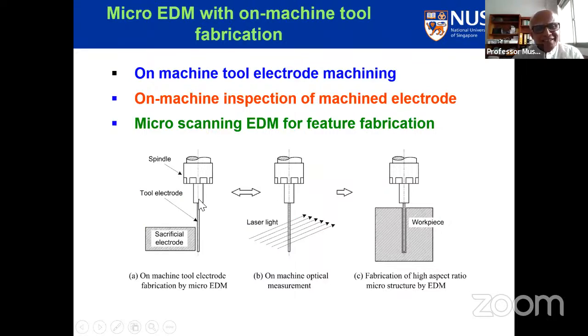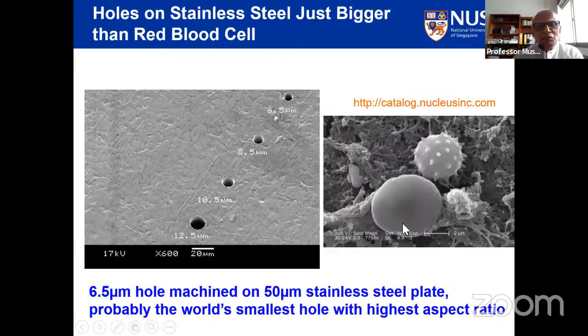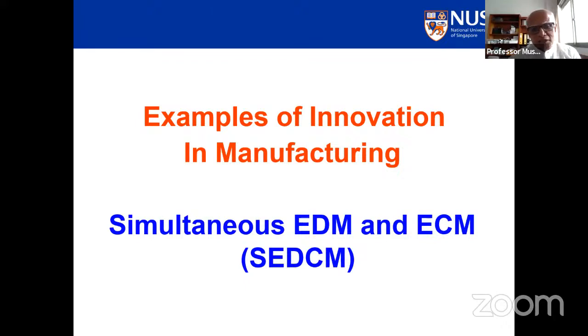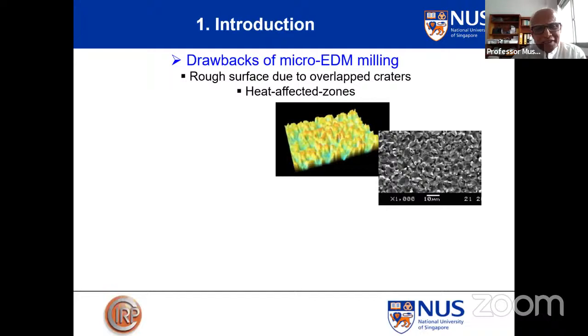This is one of the features: after machining by turning, we do EDM, sacrificial EDM. We reduce the diameter and scan it at every stage. And finally, we machine the hole by EDM, and the hole is about 6.5 micron. But with just conventional machining, without hybrid thinking, making a 6.5 micron hole is almost impossible. And it's still holding the record as the smallest hole with the highest aspect ratio. While developing the machine, our objective was to do hybrid machining. We tried to hybridize many processes, even EDM and ECM were brought together to do hybrid machining. And it's been presented in many places. I will not go into details of it. This is the EDM surface.